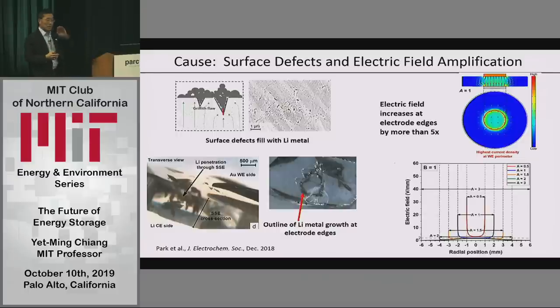So it turns out that these surfaces of solid electrolytes where the lithium metal meets this solid, it's always defective to some extent. If you think of it as having flaws, like I show you here, this is very much like how brittle materials fail. They fail because of the surface flaws, not the bulk properties. So you have surface flaws that are the initiators, the sites where defects propagate from. And what happens in this electroplating process is that we first fill those surface flaws. And then what you have is a metal asperity, which to all the electrical engineers in the audience will look a lot like a field emitter. And so we are depositing lithium metal at an asperity that's like a field emitter, and so that's where the metal deposits first.